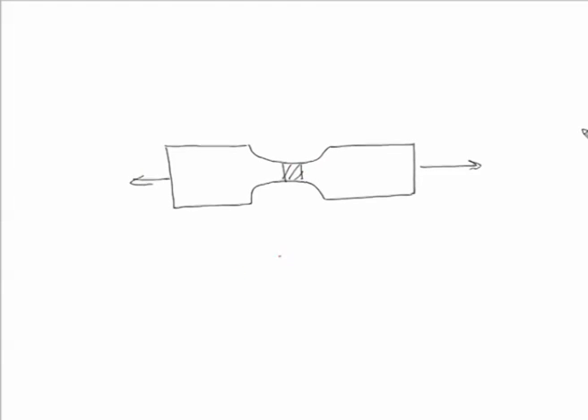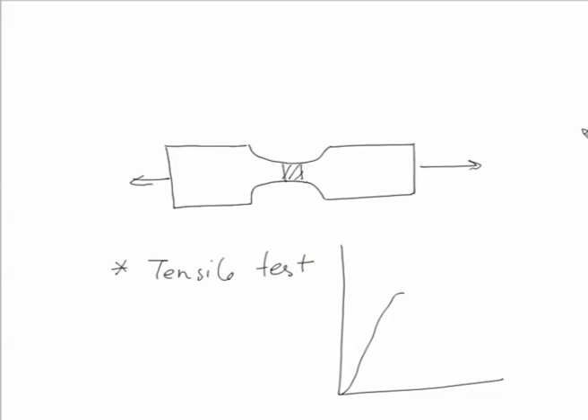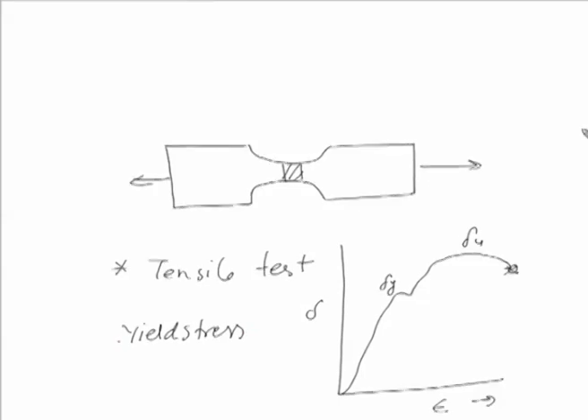So, the first step is to conduct the tensile test of the specimen. When the tensile test is conducted, it will give us a stress-strain curve of this kind. This will give us the yield stress, ultimate stress, and the percentage elongation corresponding to this point. The information related to the yield stress of the material is used for conducting the fatigue test.